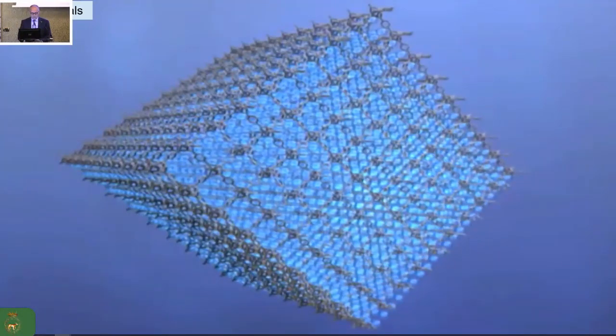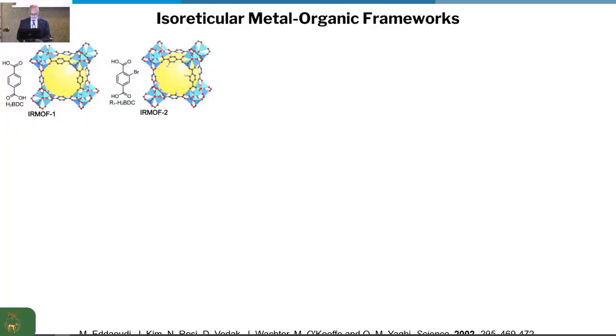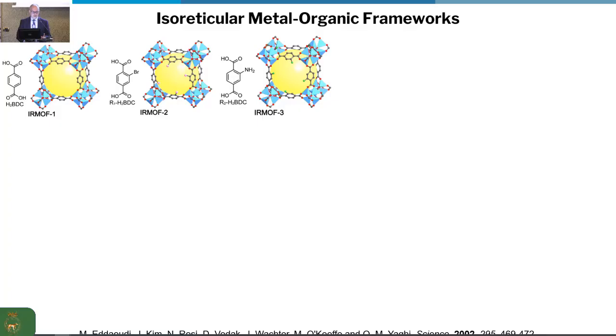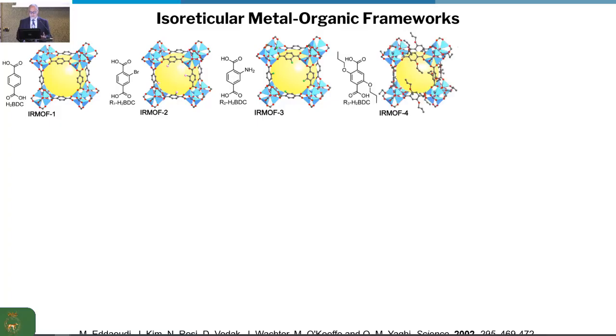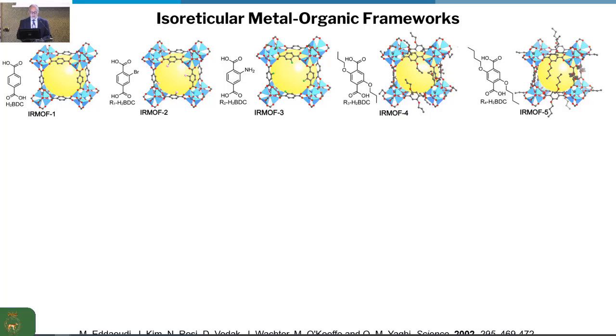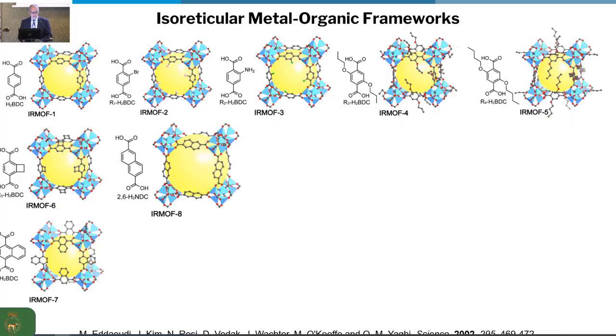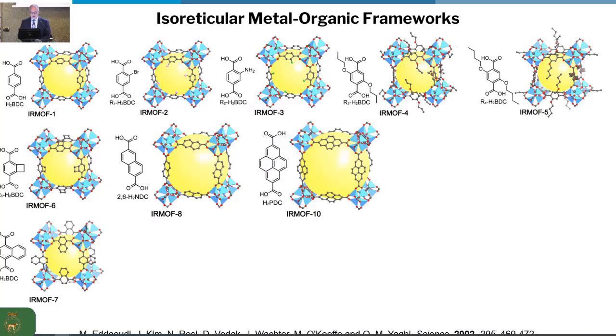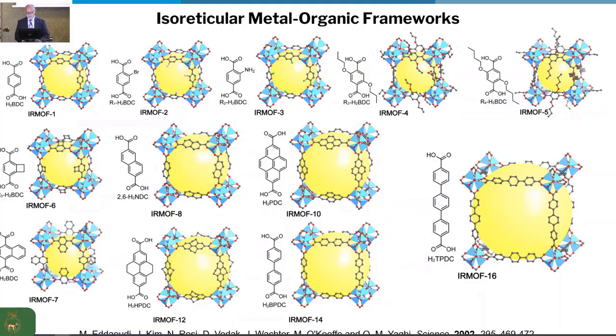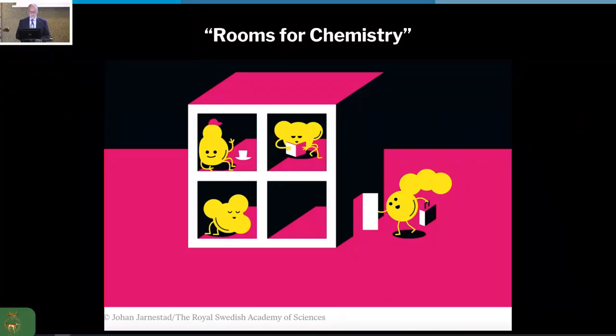Okay, so it didn't take long after that to show that in fact, like in all chemistry, once you know how to design one thing, then you could extend it to designing others, but now with different functionalities, crafting the interior with different functionalities, okay? Also, you can expand them by using progressively larger and larger linkers. So that showed that you could design materials, you could design their interior chemically, you could design the pore size, and it was the very first time in chemistry where this is possible beyond the molecule, to be able to do this with extended structures.